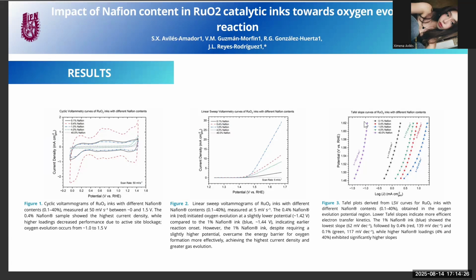Cyclic voltammetry results showed that the 0.4% NAFION ink reached the highest current density among the samples. Higher NAFION loadings like 4 and 40% reduced performance due to active site blockage. Linear sweep voltammetry showed that 0.4% NAFION initiated OER at 1.42 volts, slightly earlier than the 1% NAFION ink. However, the 1% ink achieved the highest current density once the reaction started.